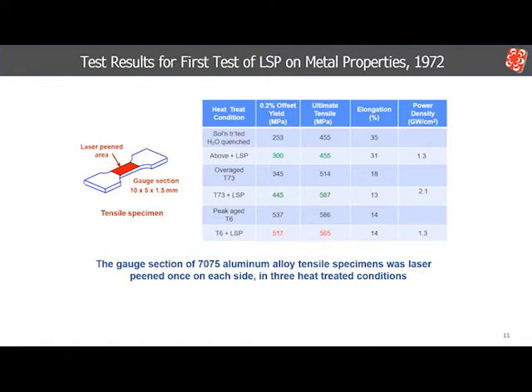The specimens were given several different heat treatments. The solution treated and quenched condition has the lowest strength because there is no precipitation hardening. After laser shocking, there is some work hardening and loss of ductility. The stronger overaged condition showed a significant increase in the yield and ultimate strength with a small loss of ductility. The increase in strength occurs because the precipitates generate a significant increase in the dislocation density when laser shocked.